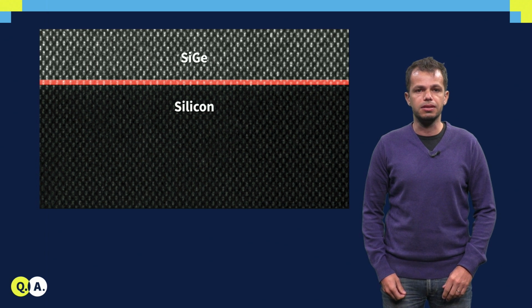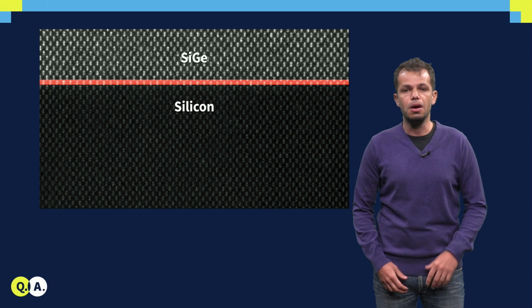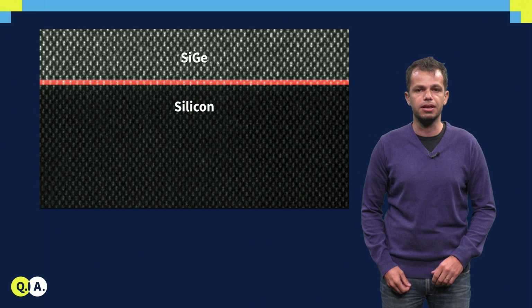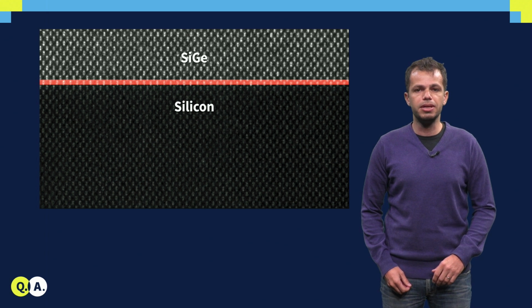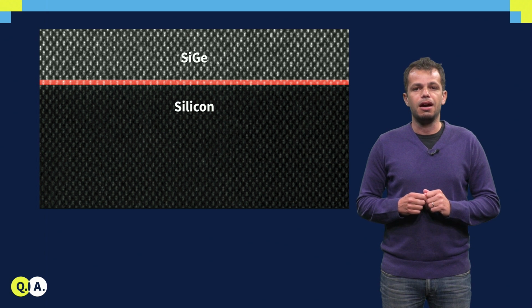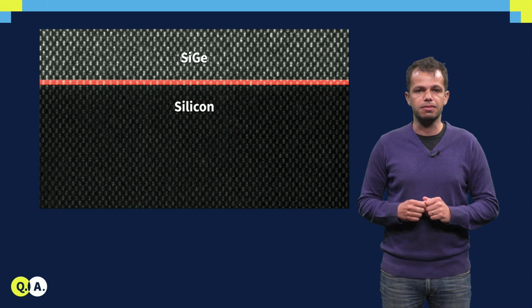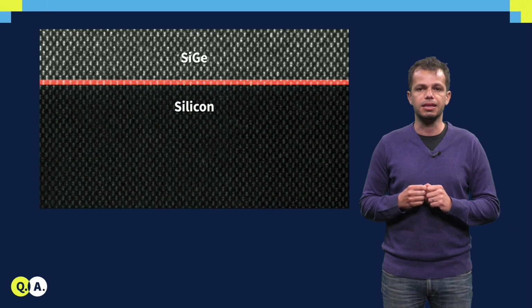Once we make our crystal into a silicon heterostructure, we usually break it and have a close look at it from the side with a high-resolution electron microscope. We call this microscope a transmission electron microscope, or TEM. Its working principle is based on electron diffraction, another quantum effect, of an electron beam passing through a thin piece of material. The spatial resolution is so high that we are able to see atomic arrangements in the lattice.